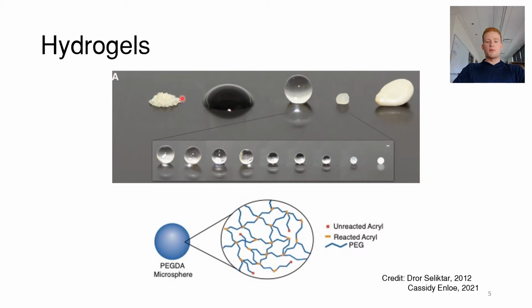Here you can see a prepolymer powder, an unpolymerized hydrogel droplet, a polymerized hydrogel particle, a dehydrated particle, and a seed here for reference. Hydrogels are photoactive and are generally fabricated on the scale of 30 to 1,000 microns. Manufacturing them smaller than this is usually difficult and slow, but miniaturizing them has many benefits.